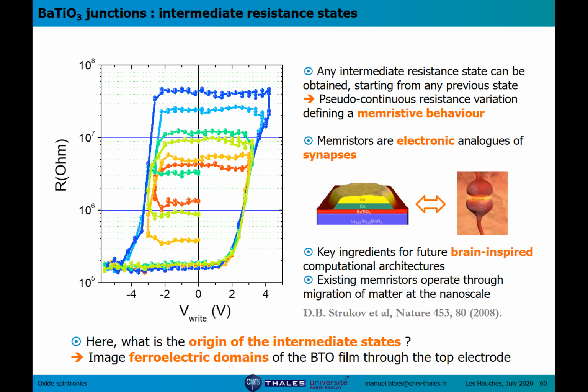Maybe you know that in other oxide memristors, for instance based on titanium oxide, the different resistance values are associated with different levels of oxygen vacancies or different positions of the oxygen vacancies. So basically you apply voltage and you generate oxygen vacancies, or you move oxygen vacancies across the TiO2 layer between the electrodes. Here we think that the mechanism is different, and I want to show you this. For that we had to devise a setup. This was done by Vincent Garcia and Stéphane Fusil to pole the junctions, measure the resistance level, and also image the ferroelectric domains in the barium titanate film through the top electrode.